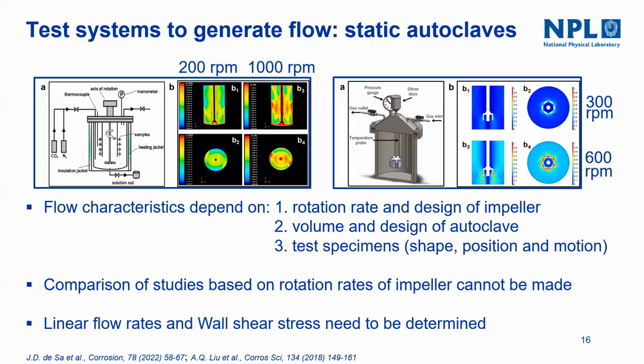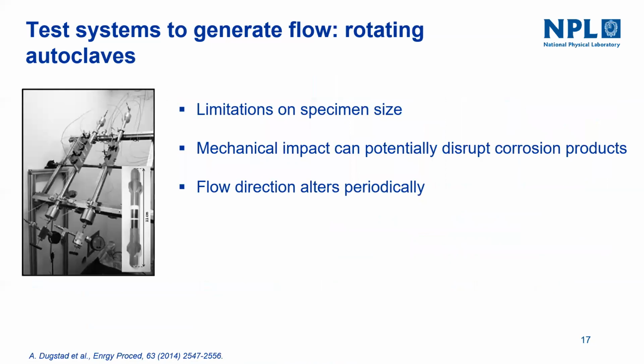So what we need to know is understanding the linear flow rates, and the wall shear stress also needs to be determined. So Dugstad et al. have also generated the flow using rotating autoclave systems where the test specimens are loaded to the specimen holder, and these autoclaves are continuously rocked or rotated. So you can generate a better fluid flow around the specimen.